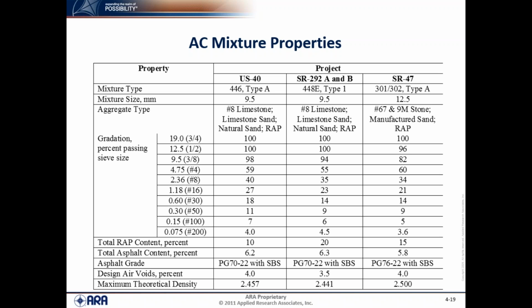Conversely, on State Route 47, it was a 12.5 millimeter mix. The big difference, or one of the differences between State Route 47 and the other three project locations, is the PG grade of the asphalt. And where we have a lot more traffic, a lot more turning movements, in terms of the asphalt grade, a PG 76-22 was used. On the other three projects, a PG 70-22 was used. The other item, since this was a larger nominal maximum aggregate size mix, it is a little bit coarser for some of the larger sieves, but when you get down to the finer sieves, it was basically relatively similar to the State Route 292 projects. It had about the same percent passing in terms of the smaller sieves for the finer aggregate.